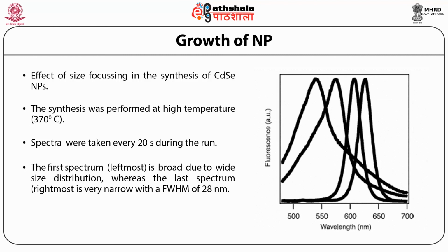In this example, the synthesis was carried out under conditions that favor size focusing. The nanocrystals were synthesized at a very high temperature, which reduces the nucleation event to a very short time span. Also, the concentration of monomers was sufficiently high to prevent the system from entering the broadening regime.